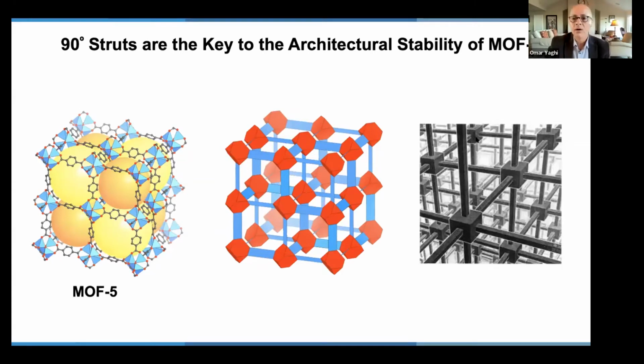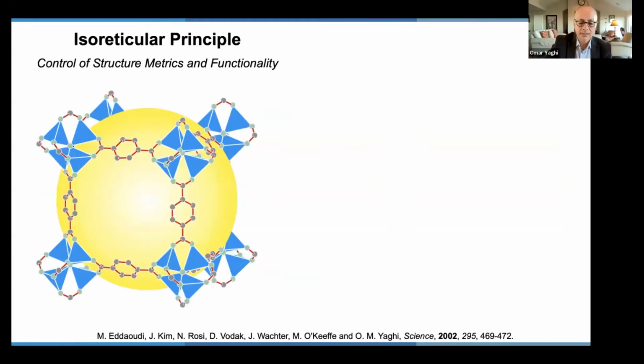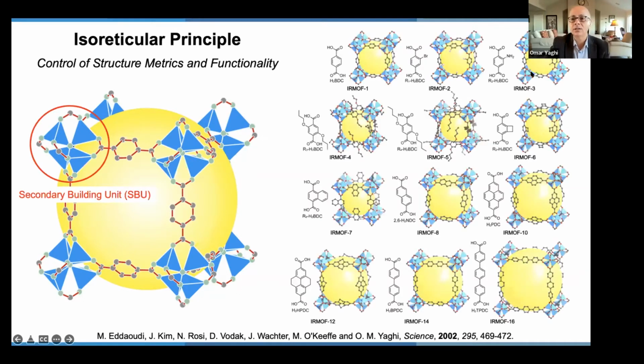But in so doing, you have exposed the interior of your crystals. Your crystal's interior is riddled with openings, such as what you see here. And to prove that, I will show that shortly, but before I get there, I just want to say that once you know the conditions under which to make this linkage, then you could employ a linker that has different functionality and therefore functionalize and craft the pores. This becomes important later when we do CO2 capture, as well as by using longer linkers, you can make larger pores so that you can incorporate progressively larger and larger molecules.